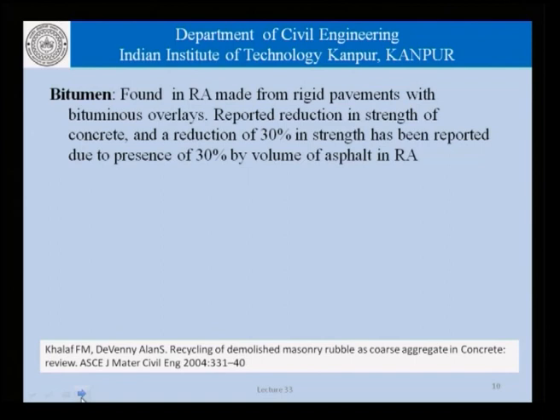Now, coming to a few impurities that are present or that could be present in recycled aggregate, one is bitumen. This will be found in recycled aggregate made from rigid pavements with bituminous overlays. A reduction of 30% in strength of concrete has been reported due to the presence of 30% by volume of asphalt in recycled aggregate.